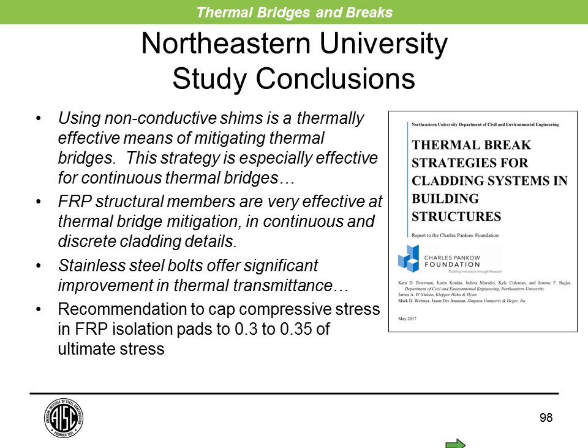And they also recommended capping the compressive stress in the fiber-reinforced plastic to about 30 to 35% of the ultimate compressive strength of that material to eliminate the chances of creep over time. They also found that stainless steel bolts offer significant improvement on the thermal transmittance through the connections. They also found, which was a surprise to me, that thermally improved bushings offer relatively little mitigation benefit. So that's something that I'll be changing in my practice going forward, is to eliminate the bushings and to use stainless steel fasteners.